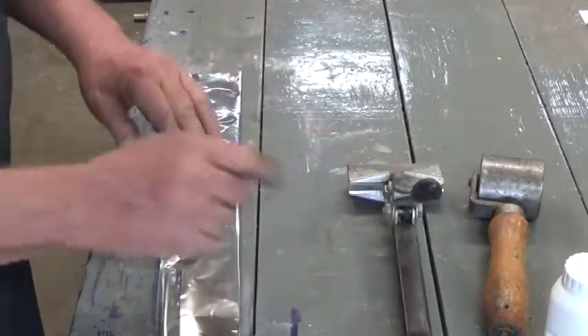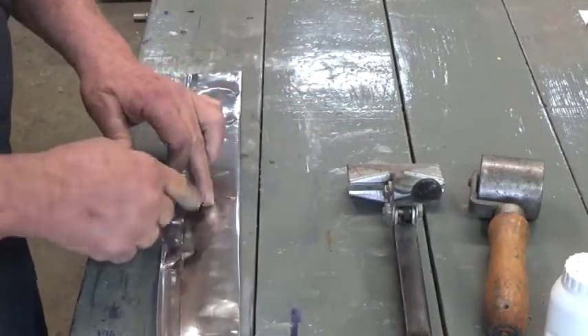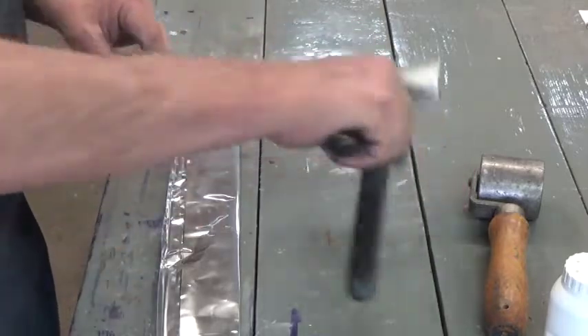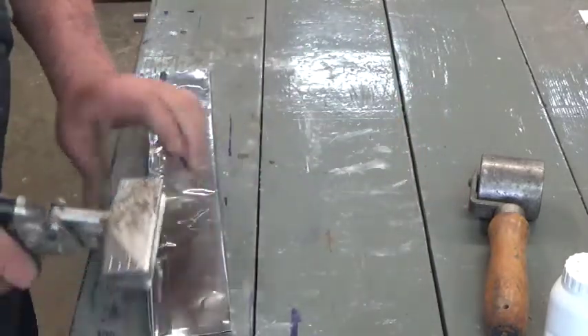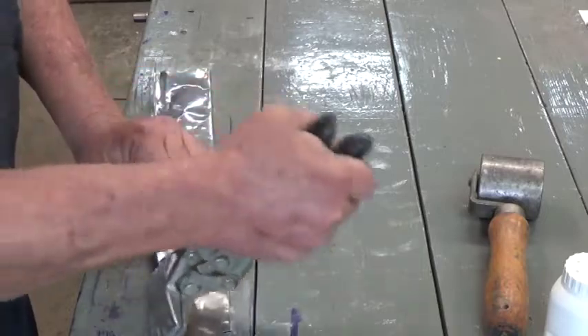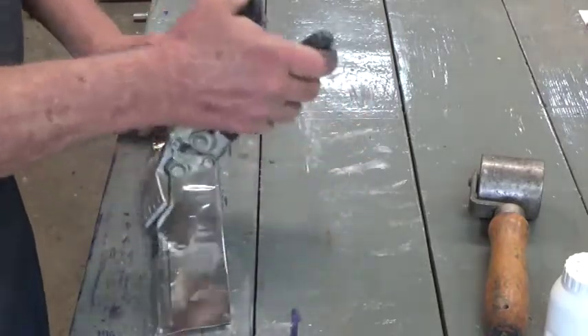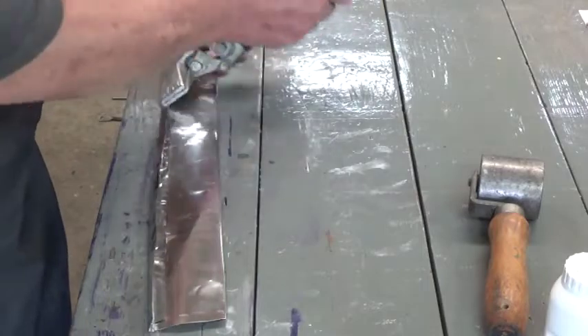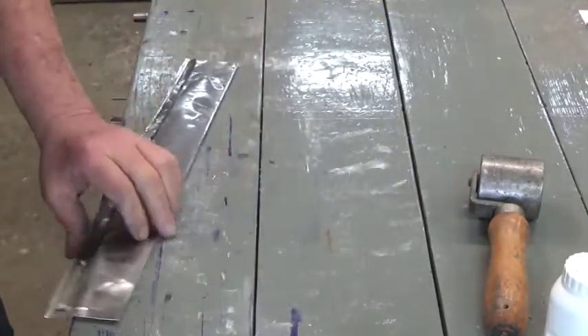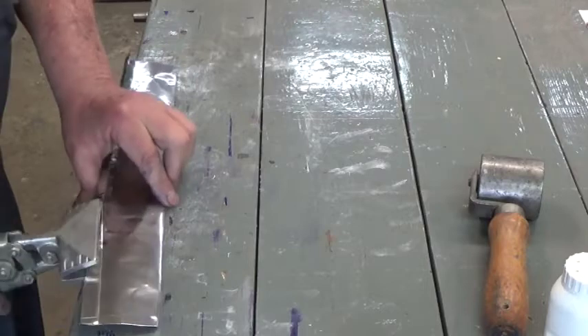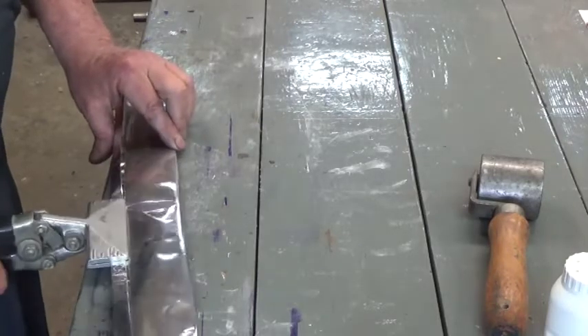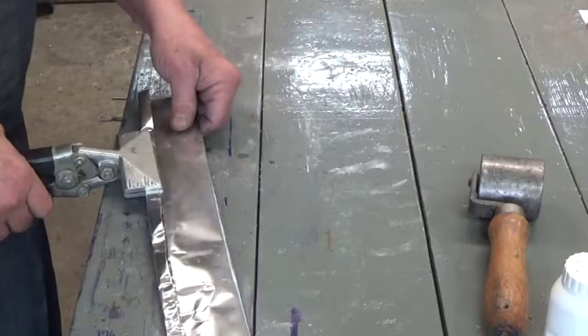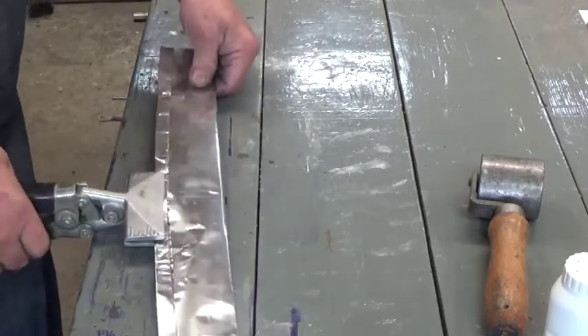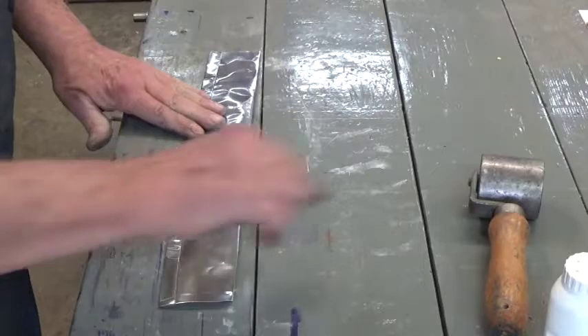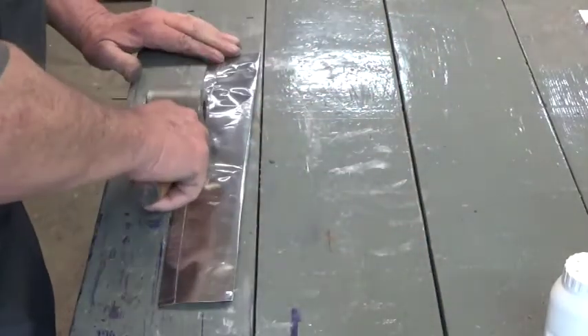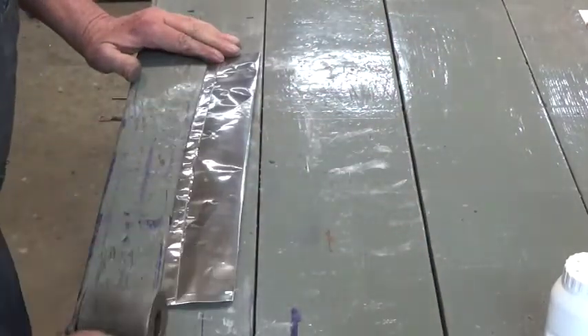And what will happen is right at that spot you'll get a big ring of decarburization that you have to grind off. So we avoid that. We put a lot of work into it to this point, and so let's not undo what we've done. So I just get that started over on that double fold where I can grab it now and just crimp it shut. If you didn't have sheet metal pliers like I'm using, you can just use a roller, and I still do. You just want to get out any of the excess that you can.